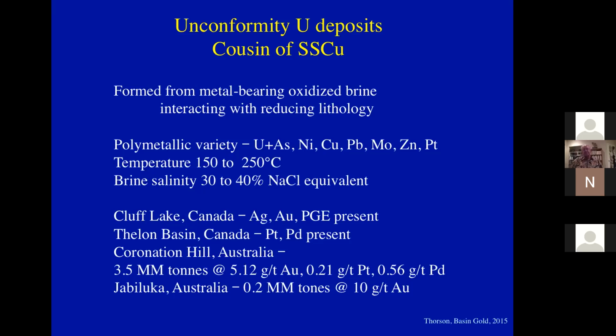So what other deposits contain precious metals that were deposited from low temperature brines? And those that I found first are the unconformity uranium deposits, the most famous of which are up in the Athabasca Basin, Canada. Some of the others that are less famous but more rich are in the Alligator River area of northern Australia. They also were formed by metal-bearing oxidized brines that interacted with reducing lithology. In this case, when the brines came in contact with a graphitic horizon in the basement, they deposited metals in the sandstones immediately adjacent.